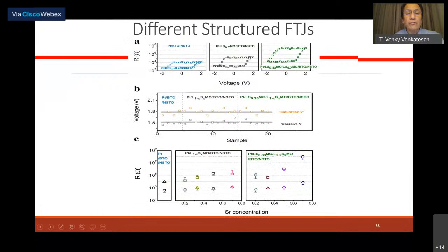All right. Now, how does it behave in the three classes of devices that we made? Very simple: platinum, BTO, and the NSTO, which is the conducting bottom electrode, or platinum with one extra oxide introduced between the BTO and the platinum. And here we have introduced two oxide layers. What we see is that exactly as I increase the number of layers, the on-off ratio does indeed get bigger and bigger. But what about the switching voltage, the saturation voltage? Absolutely no change at all. The switching voltage and the saturation voltage are identical for all three different types of device structures. So it is only controlled by the ferroelectric. The ferroelectric determines when it switches and when it reaches saturation.